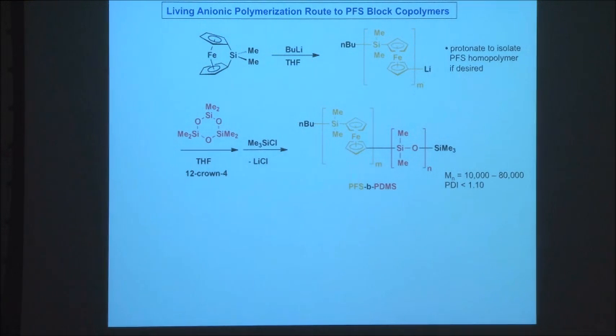They don't spontaneously terminate. And this allows you to add another monomer so that it will grow off the end. So you polymerize off the end, and you can make a block copolymer which you eventually terminate, but deliberately, by adding for example trimethylsilyl chloride, and this will give you a TMS group at the end. So this living route allows you to make block copolymers, and it also allows you a lot of control over the structure of this material. So this is a very controlled synthetic method.